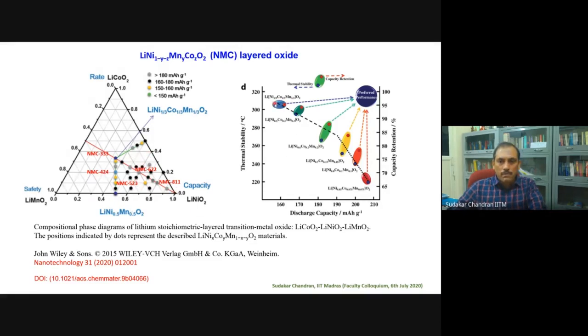But then what happens if you try to increase the discharge capacity? Then the thermal stability decreases and also the capacity retention decreases. But then we want the preferred performance to be somewhere there. So there is always a give and take that happens. So a lot of studies are still going on to find out the suitable material which can give very high capacity and also can retain the capacity over large number of cycles in the batteries.